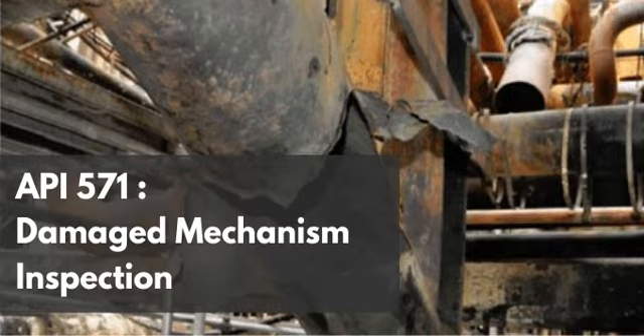Without a doubt. When you cut a circular hole into the thick shell of a heat exchanger and weld a cylindrical pipe into it to form a nozzle, you completely disrupt the continuous distribution of pressure-induced stresses. Because the internal pressure of the vessel creates hoop stress, the force trying to burst the cylinder open, and longitudinal stress. Right, and at the exact edge of that bore, the hoop stress is magnified significantly, often by a factor of 2 or 3 compared to the nominal shell wall. And because it's a reboiler exchanger, we have to layer on thermal stress, too. Exactly. The shell might be thick and massive, taking a long time to heat up, while the thin-walled nozzle pipe heats up very rapidly as the hot fluid flows through it.